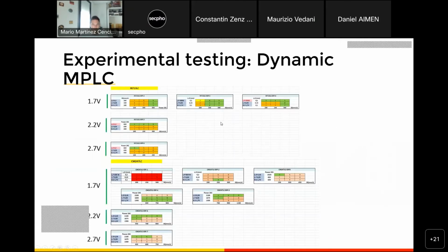And I will not spend so much time here. This is just for you to know that we carried out a huge process parameter mapping for both materials. So on the top side, you can see the experiments carried out for the Inconel 713, and as you can see here, we tested the whole range of the dynamic MPLC. So from 1.7 volts, where the primary beam receives more energy and the secondary beam has a limited energy, let's say, and up to 2.7 volts, where we have a power distribution of 23-77. So the secondary beam has more energy in this case.